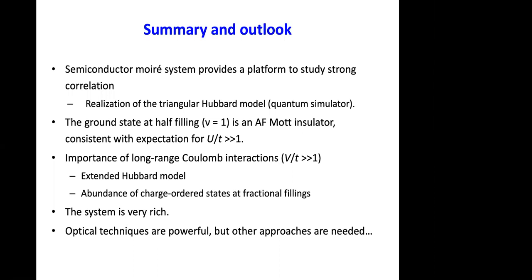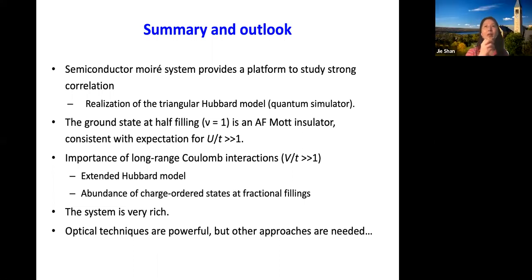So, Jie, I think I missed your answer to a previous question. What was the spacer for the sensor layer? Oh, okay. Is it the hBN thickness? Yeah. So the hBN electronically separates the sensor and the system you want to probe. But you don't want the hBN to be too thick, because you still want to be within the exciton Bohr radius. For the 2S state, we're talking about something like 5 nanometers. So as long as you are within that bulk number, you are fine. The example I showed here is on the order of 1.3 nanometers.